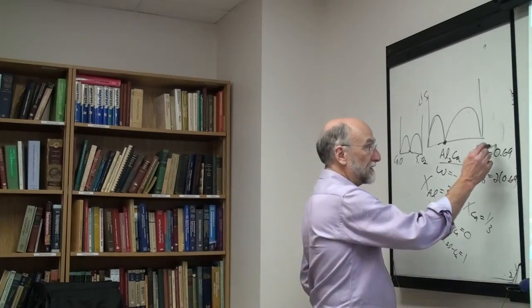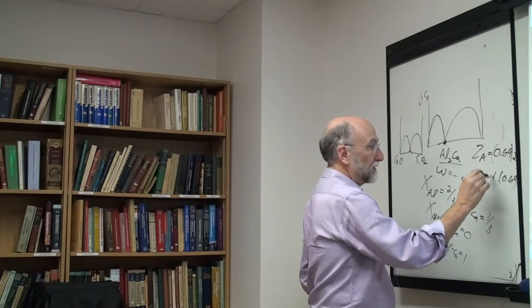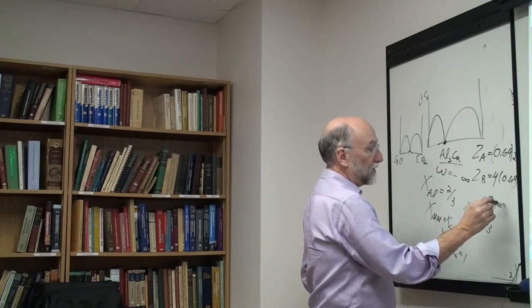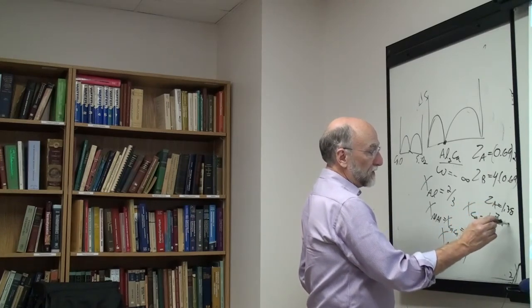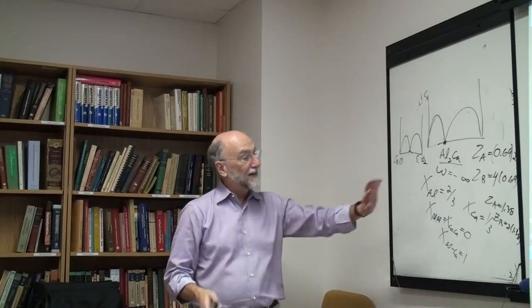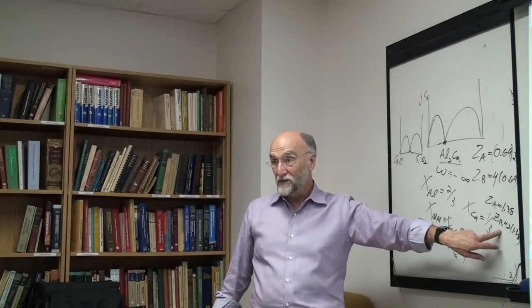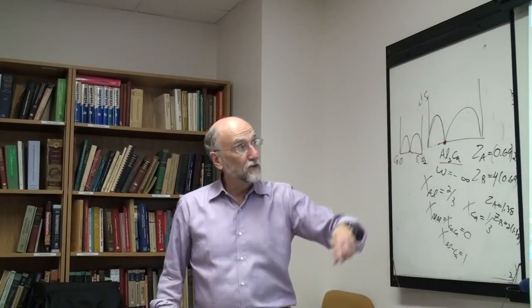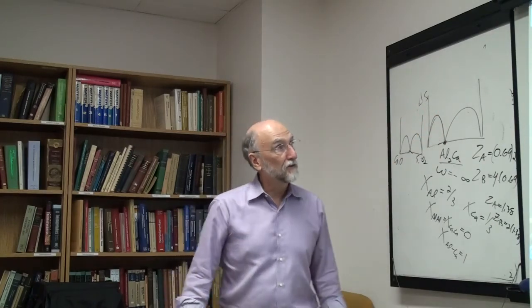Actually, sorry, ZA is that times 2. It's 2 times that. So this would be 4 times that. So ZA would then be 1.38, and ZB will be 2 times 1.38. So you end up with the Z that's not exactly an average of 2, but the ZA is less than 2, the ZB is greater than 2. There's a little formula here which will show you exactly how to do it. We can talk about that on Thursday.